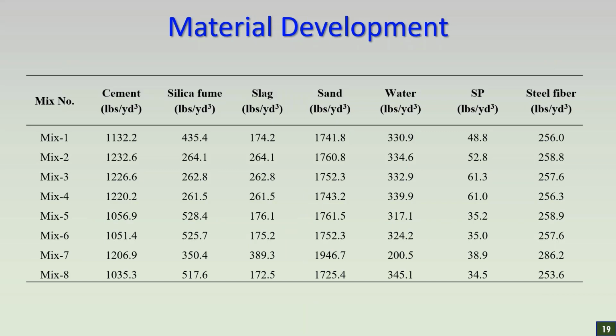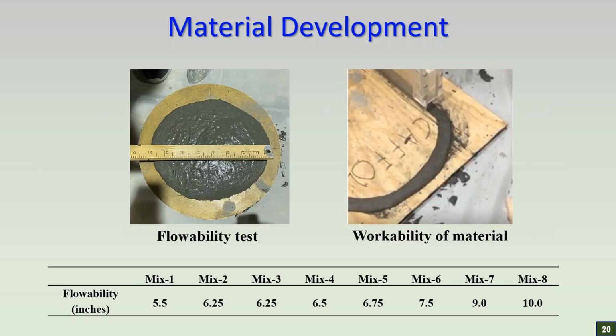Now, for the development of the material, we tested a lot of mixes, and some of them are shown here from mix 1 to mix 8, on the basis of the workability and the flowability of the material. These are the compositions shown for these mixes. For all of these mixes, mostly the binder to aggregate ratio was kept as 1, and 2% volume of steel fibers was used. For the mixes shown in the last slide, the flowability values range between 5.5 inches to 10 inches.